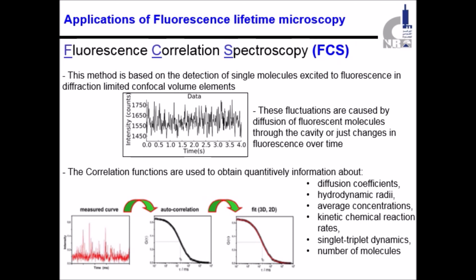These fluctuations are caused by diffusion of fluorescent molecules through the cavity or just a change in the fluorescence over time. The correlation functions are used to obtain quantitative information about diffusion coefficient, hydrodynamic radii, average concentration, kinetic chemical reaction rate, singlet-triplet dynamics, and number of molecules.